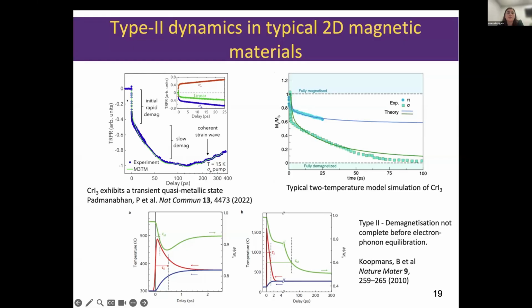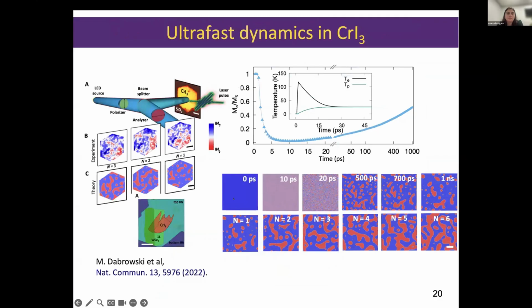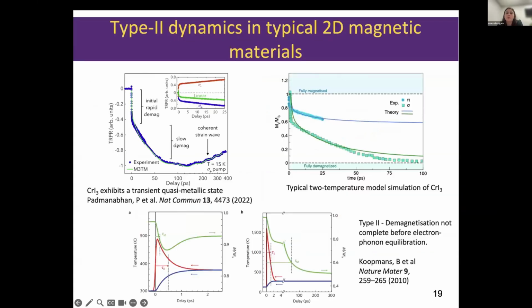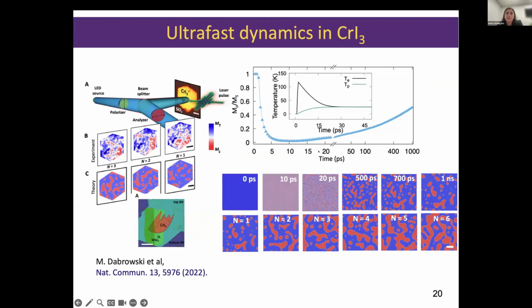So this is one example of chromium triiodide, where we show an initial rapid demagnetization and then a slow demagnetization process. So we are able to reproduce this type 2 demagnetization with our atomistic simulation as shown here. However, when talking to our collaborators in Exeter who performed experiments on this type of system, they observed some rich domain information which we were unable to see in these initial simulations.